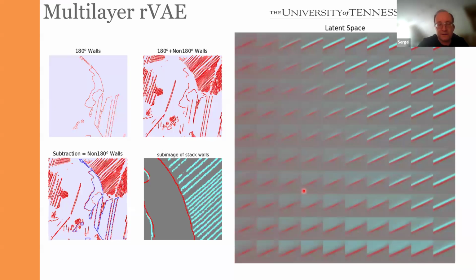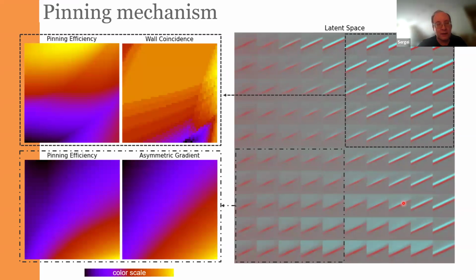So what it means is that this domain wall is not pinned, which basically means that we can choose the center, but the edges kind of move in any which direction, and therefore they average to a much lower value. So after a while, if we look at something like this, it's a little bit abstract representation, but once you think about it, then it maps exactly onto the physical mechanism that we are interested in, and we can visualize them, quantify them, and kind of make sense of what they mean.